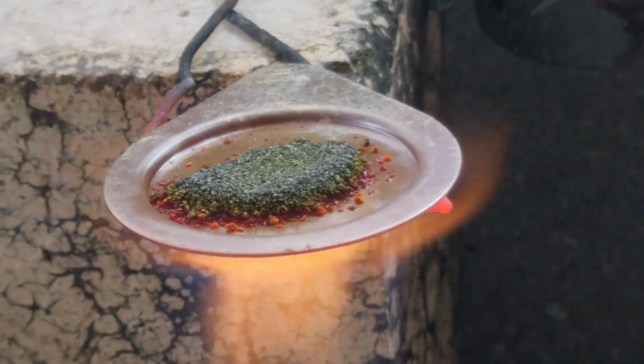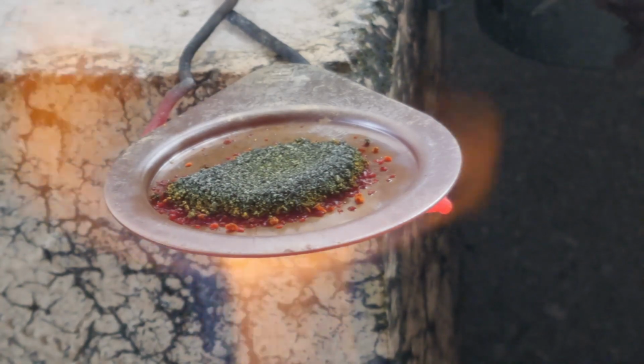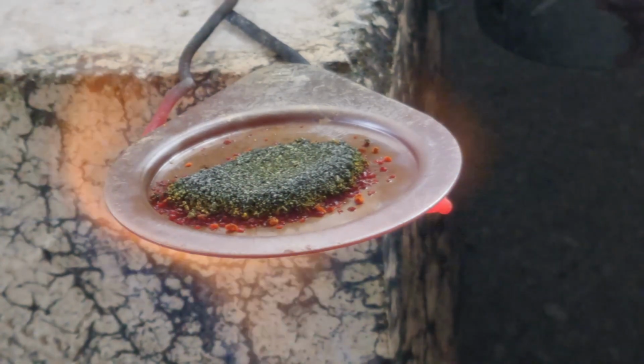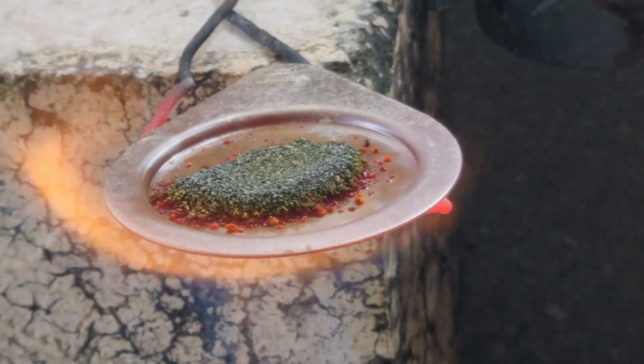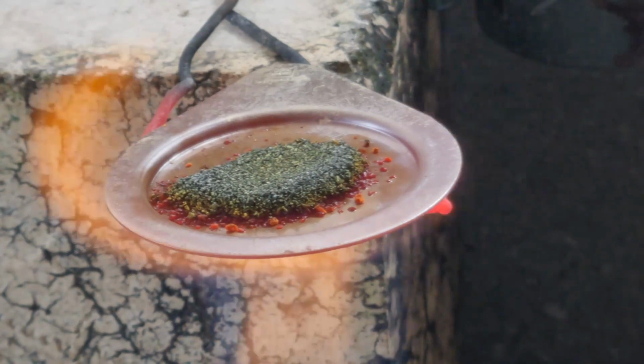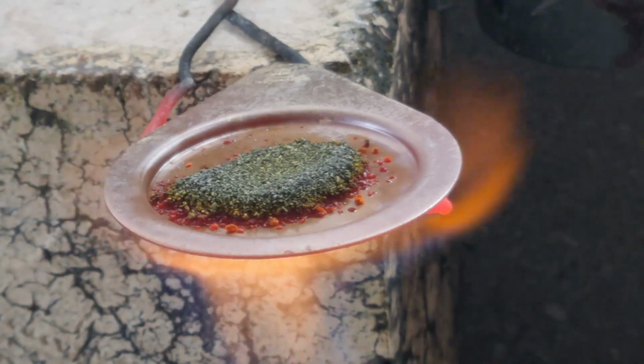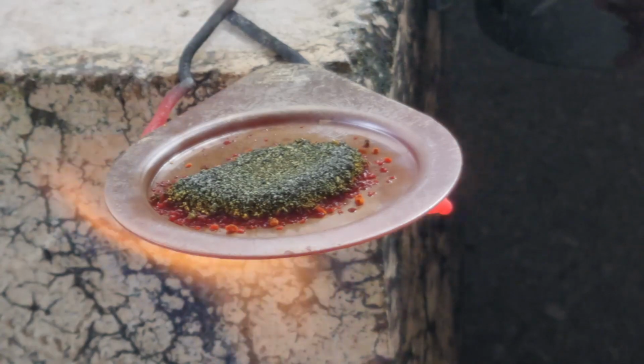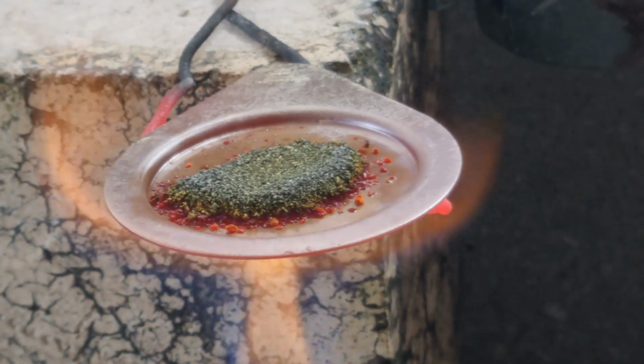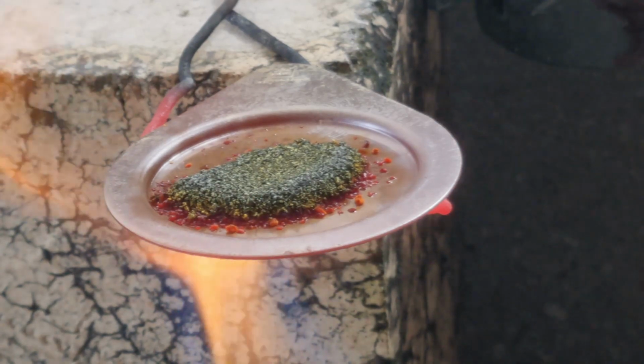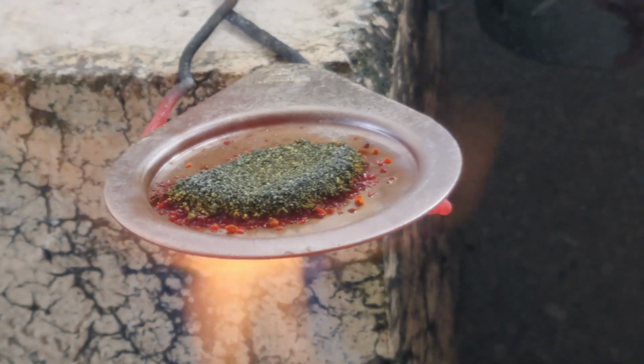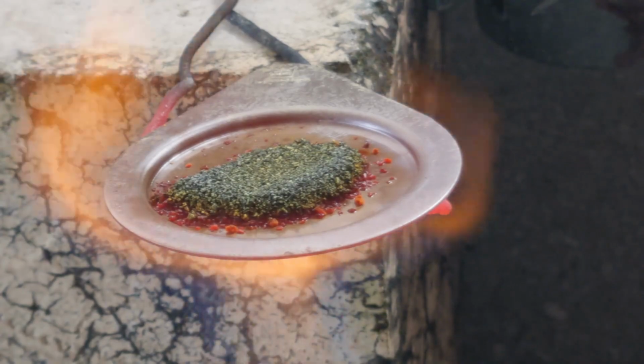This melt at first inhibits the diffusion of oxygen from the air, but when heated further, the agitation produced from the convective currents and release of carbon dioxide counteracts this. Although the magnifying glass method is the fastest and easiest, the same result can be achieved by heating the mixture under a Bunsen burner or placed into a muffle furnace for several hours at 800 to 900 degrees.